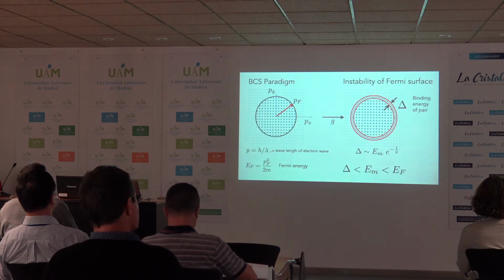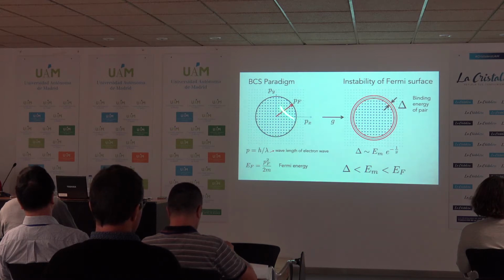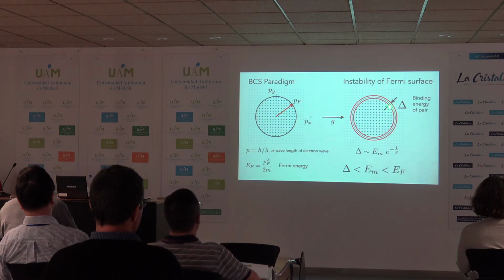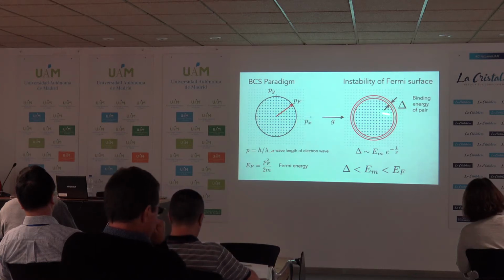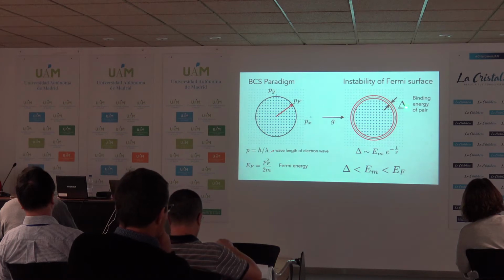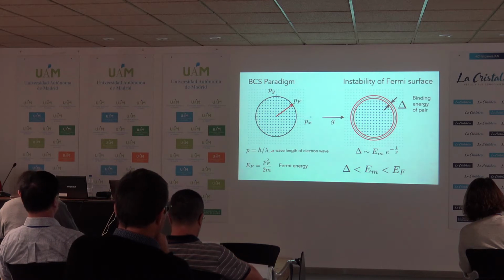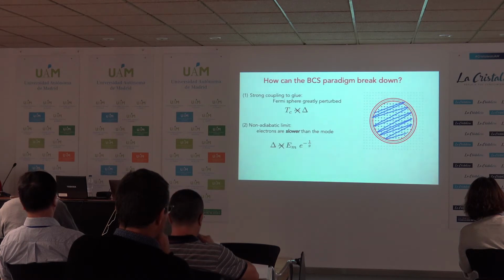So very quickly about the BCS paradigm, which you all know, you start out with a large Fermi surface, and when you turn on some coupling, some attraction, it opens a gap on the Fermi surface. The gap scale is much, much smaller than EF. That's when your Cooper pairs are large and the BCS paradigm works, which basically is a statement that everything is controlled by the gap, or the amplitude of the order parameter.